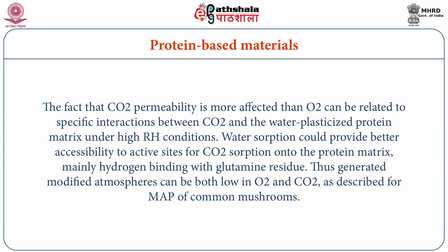Water sorption could provide better accessibility to active sites for carbon dioxide sorption onto the protein matrix, mainly hydrogen binding with glutamine residue. Thus, the generated modified atmosphere can be both low in oxygen and low in carbon dioxide, as described for modified atmospheric packaging of common mushrooms.